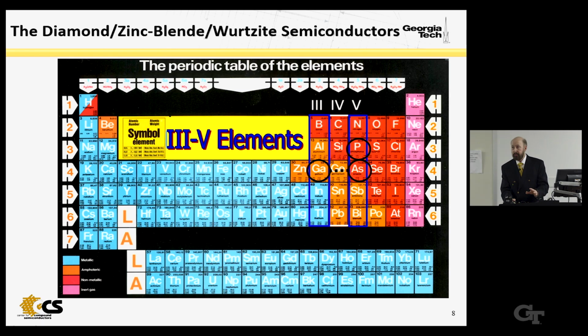And this is the first ternary that made a visible LED, gallium arsenide phosphide, red LEDs and laser diodes. If you add aluminum, you get a quaternary. This is the first quaternary, aluminum gallium phosphide arsenide, demonstrated by Nick Holonyak's group at Illinois in around 1977, or earlier, 1970, sorry. If you add indium, antimony, nitrogen, boron, you get all of these nice materials.